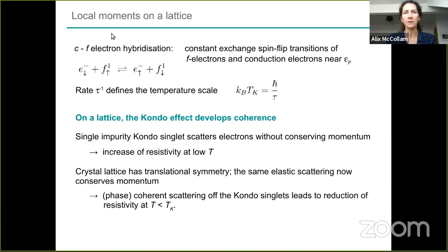So as I said, if you have a lattice and not just single impurities, you can also think of this conduction electron hybridization as a constant exchange of spin flip transitions, right? So this F electron has some finite amplitude of probability to tunnel and flip spins in this way, and you can think of the probability of this tunneling or the rate of this tunneling as defining this Kondo temperature scale. So this is basically the relevant temperature. There isn't actually another relevant temperature scale in this problem. So when you have a Kondo lattice or local moment sitting on a lattice, you have this type of interaction and you end up with a coherence at very low temperature, and then the relevant energy is given by the coherence temperature, which is the Kondo temperature.